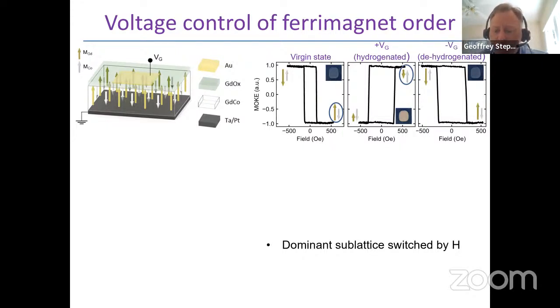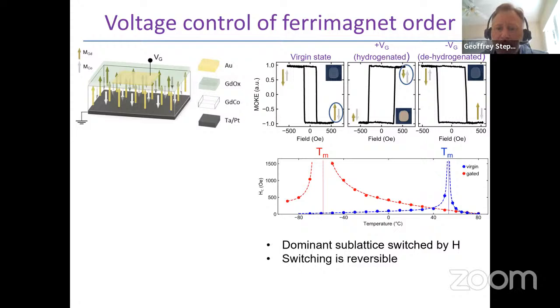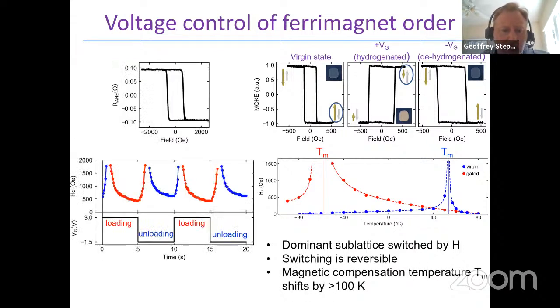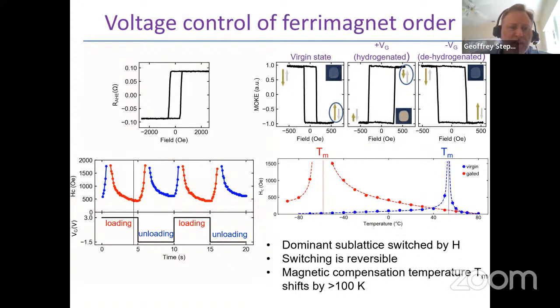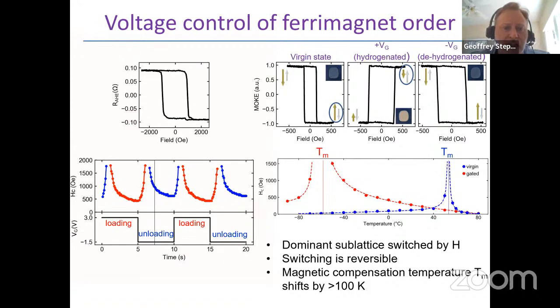So at room temperature at a given composition, we can switch the compensation state. In fact, we can, in an analog way, drive the system arbitrarily across composition. And we can control that. We can change the compensation temperature by a significant amount, by at least 100 degrees. And that was limited only by the cryostat that we have available to us. We can do this repeatedly. So by applying a gate voltage of a positive and negative polarity, you can see dynamically the hysteresis loop that we can drive it through compensation one way or the other, again at a fixed temperature.